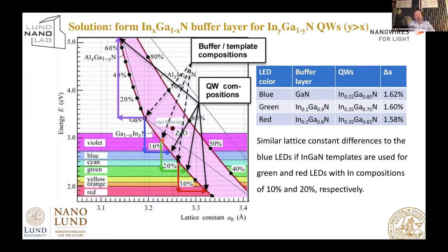For instance, 10% indium would be this point here. Assume that we can incorporate indium in the substrate, we would be able to do exactly the same exercise in terms of the materials variations and in terms of the strain and all that. And you would go horizontally out to this point here, which is 25% indium. So now we have quantum wells of 25% indium grown on 10% indium containing substrate.